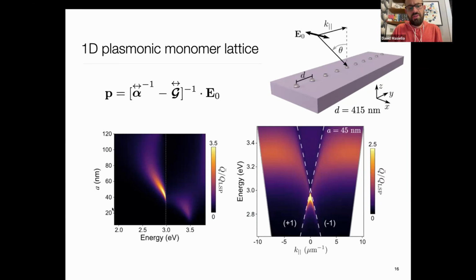And what you see is that as you start to grow the radius of the particle, for small radii, the particles are not big enough to appreciably scatter. And so you just have single particle absorption. Every unit cell is independent of the other unit cells. But as the particle radius gets bigger, such that the particles appreciably scatter, then they communicate with each other through the radiative intermediate and far zone fields. And this collective surface lattice resonance of the assembly emerges. So we grab that radius of roughly 45 nanometers, and we use that for all the calculations going forward.